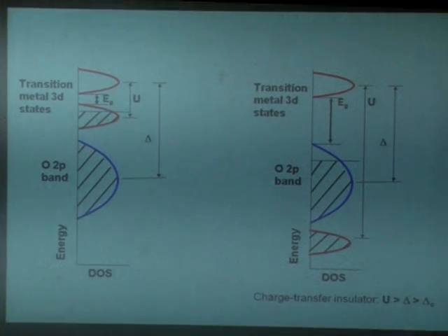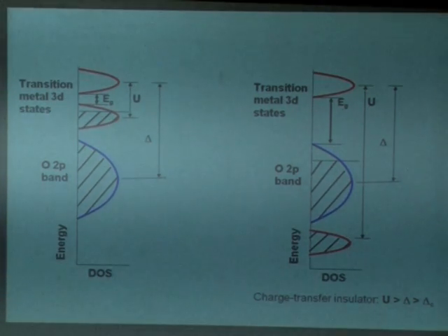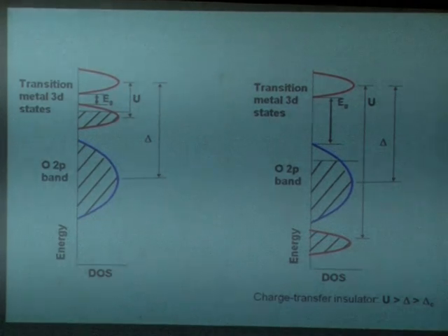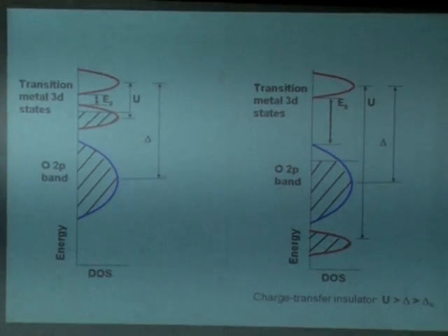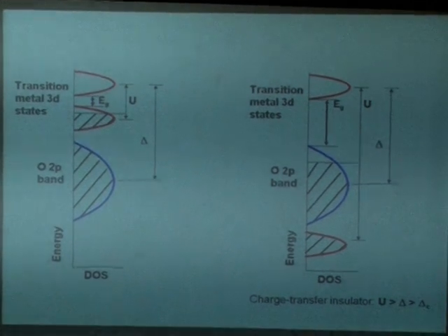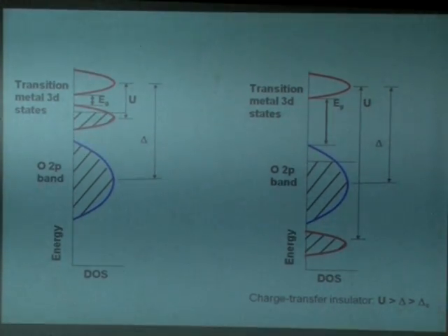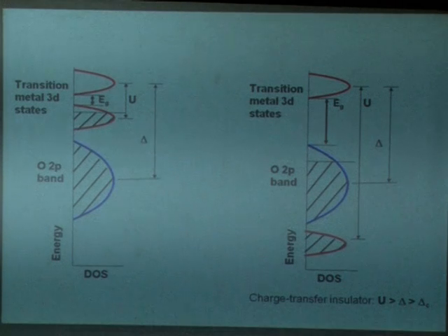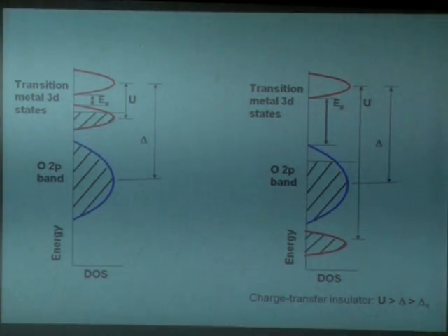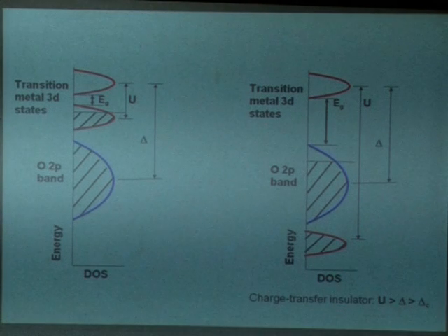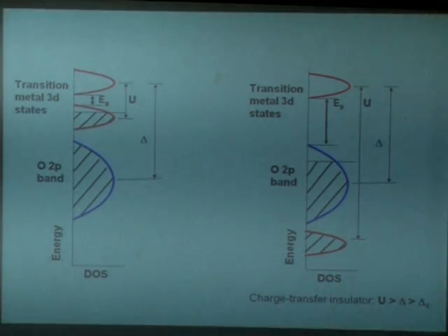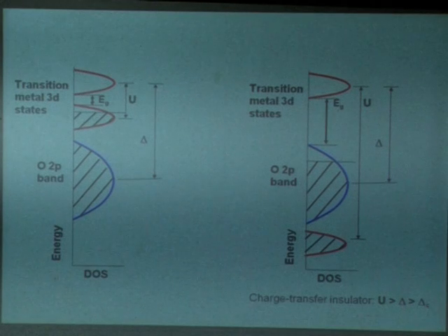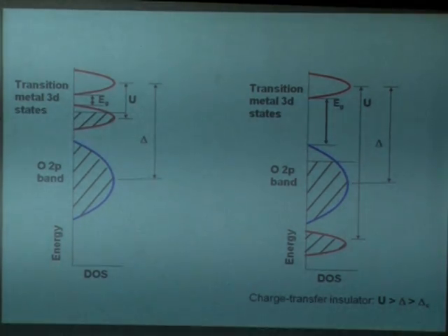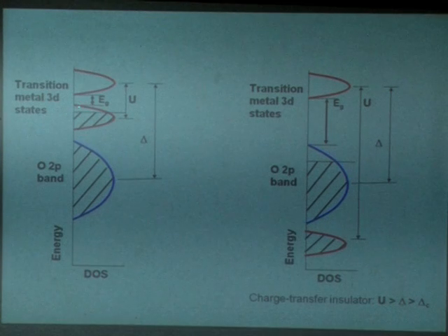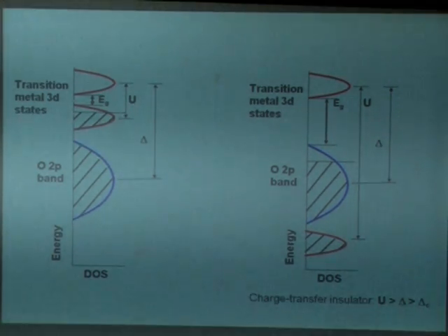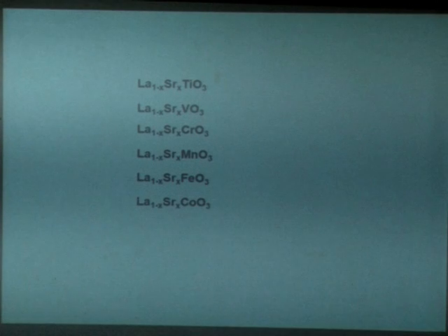In this first approximation, the splitting is unimportant. So this entire model is based on equilibrium. This is the kind of metallic state that it's saying. But what is important to see is that all these pictures tell you that as soon as I put in the slightest amount of holes, the system will become metallic. That's the reason I didn't talk about doping holes in the metal. That will make the metal metal. That's no big deal. But if you take an insulator and any amount of hole you put, immediately it will become metal. So let's go back to this and ask the question, what really happens?